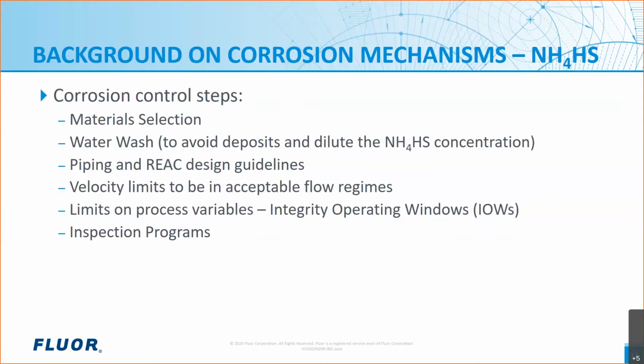We have velocity limits, mainly to try to stay in the acceptable flow regimes. We set limits on lots of process variables, temperatures, the water quality, things like that. And in order to make sure that the unit doesn't change over time, and because these variables are still within design conditions, so in order to make sure it just doesn't change by process creep, as we call that, we set integrity operating windows. There's actually an API standard on this, and the industry has adopted the acronym IOWs. So it's important to set many IOWs around the REACs in order to keep a monitor of the variables that can affect the corrosion. And then the inspection programs.